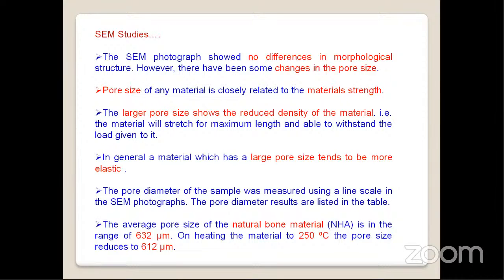So the pore diameter of the sample was measured using a line scale on the same photograph. The average pore size of the natural bone material is in the range of 632. On heating, the pore size is getting reduced. Particularly at 250 degrees centigrade, it is getting reduced by 20 micrometers to 612 micrometers.